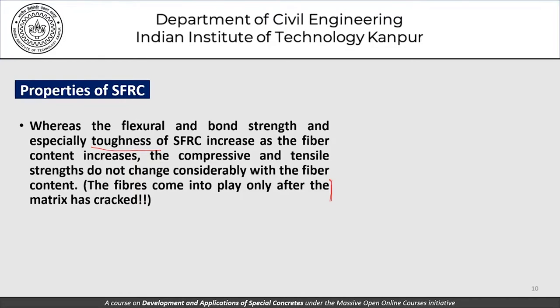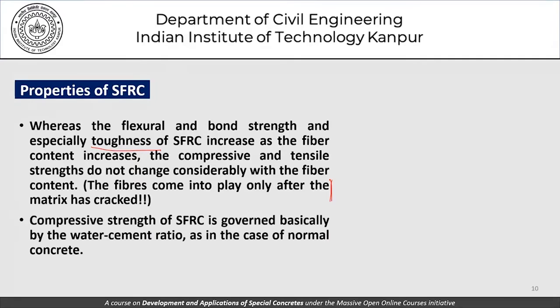The addition of fibers may not substantially increase compressive or tensile strength, but the post-cracking behavior is a completely different story. Only post-cracking do the fibers come into play and take increasing load. Flexural and bond strength, and especially the toughness of steel fiber reinforced concrete, increase as fiber content increases, whereas compressive and tensile strengths do not considerably change with fiber content.